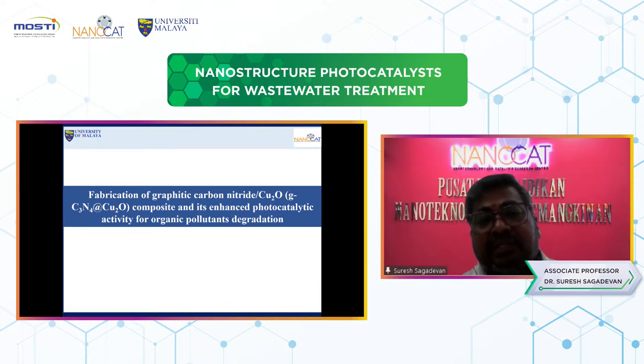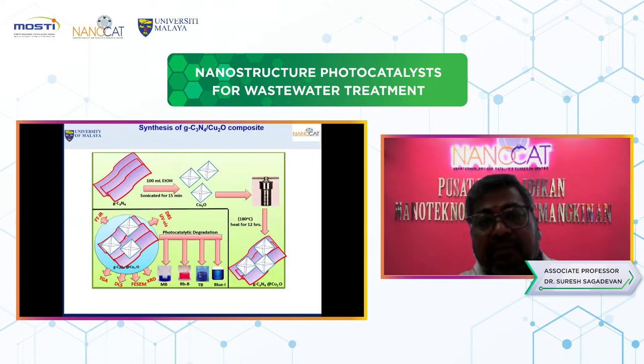When you add it with the copper oxide, how does it behave for the removal of organic pollutant dye degradation? We prepared this composite using the hydrothermal method. The graphitic carbon nitride is sonicated for 15 minutes with 100 ml of ethanol. After that, we mix it with the copper oxide solution, combined together in a Teflon autoclave, and heated at 180 degrees Celsius for 12 hours. After that, you can see the graphitic carbon nitride composite with copper oxide nanocomposite, with filter.